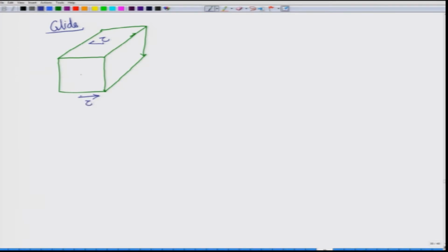So, this is the shear stress, and let us say the Burgers vector is in this particular direction. This is the shear stress on the 2 sides being applied like this, and simultaneously for balance you will have to have the shear stress on these 2 planes, but which we are not right now describing. Now, when this deforms, the final shape you can imagine would be so. Let us say that one dislocation has moved. If one dislocation had moved, this would cause a 1b step in this bar.